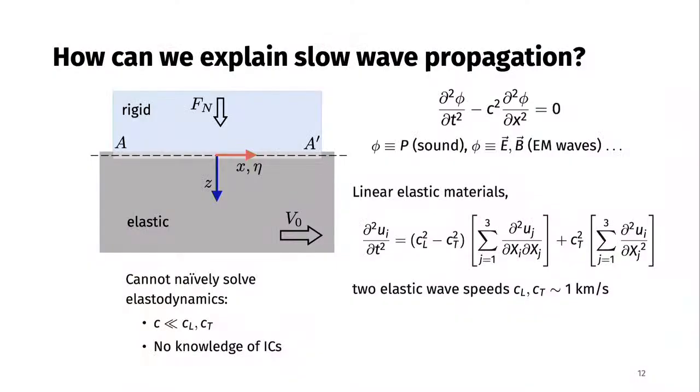Right? Now, the problem with trying to recover these types of waves from elastodynamics is twofold. Firstly, of course, the wave speed is very low, so there's really not much you can do because any wave that you try to describe with this elastodynamic framework will depend on those two wave speeds. The propagation speed will depend on those two wave speeds. And the second problem is we don't know how they nucleate, right? This is really the key that we're trying to address in the second part of the talk. So the initial conditions for how these waves form, we don't have much of an idea based on these experiments.